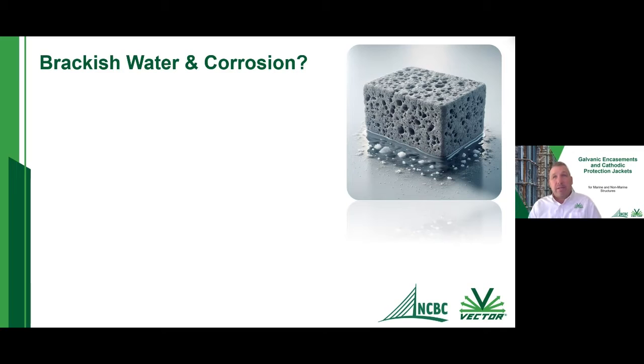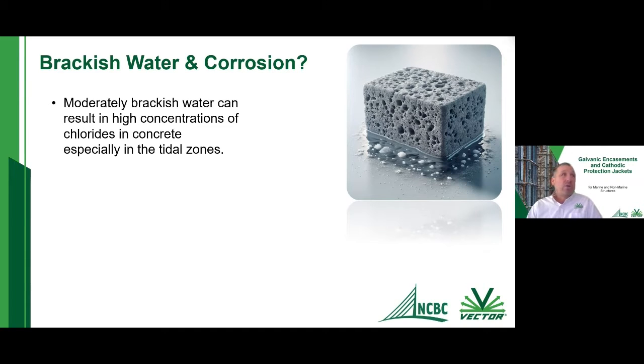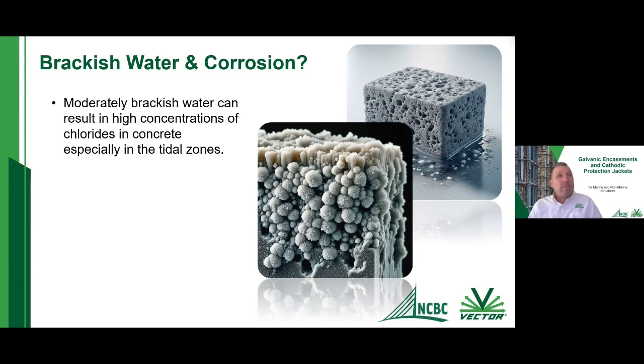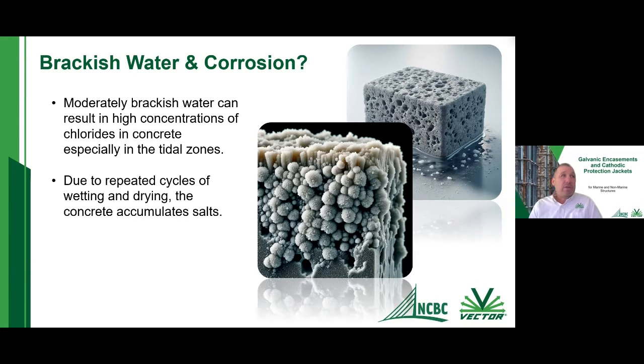In a marine environment, you can be exposed to brackish water, and the brackish water may not have very high levels of chlorides in it. It may just have some moderate levels of chlorides, nothing near the point that's really going to cause a huge corrosion issue, say for exposed steel. But because the concrete is very porous, this brackish water goes in and out of our concrete surface, and due to this repeated wetting and drying cycle, the chlorides remain in the concrete.